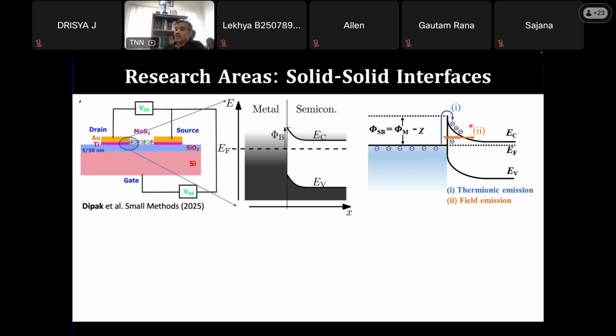But if the semiconductor is not very heavily doped, this thickness will be quite high, because the spatial width of this diffusion barrier will be quite high. To compensate the charge in this particular junction, you use a large amount of electrons at the semiconductor junction. So the spatial width of this barrier will be quite high. Then the electrons cannot tunnel through the barrier and cross the semiconductor to have the transfer. So the field emission will be quite poor. Thermionic emission will still be happening.